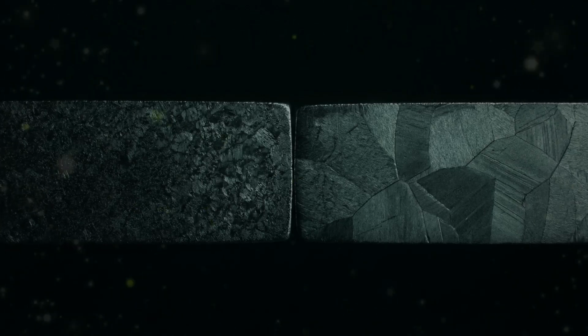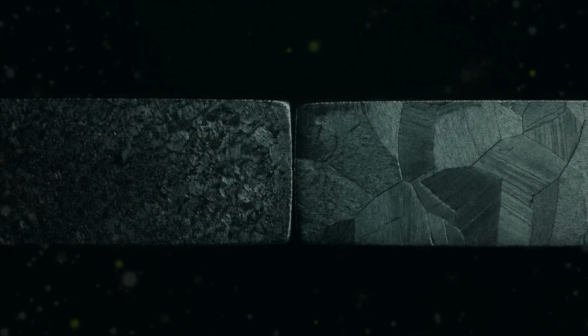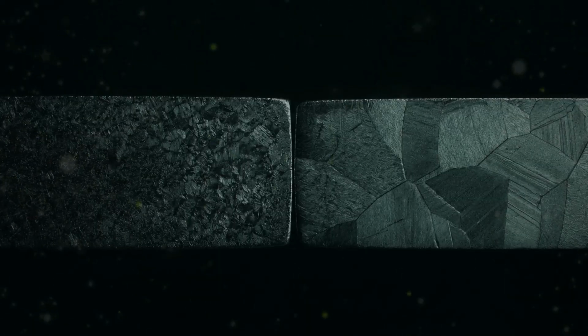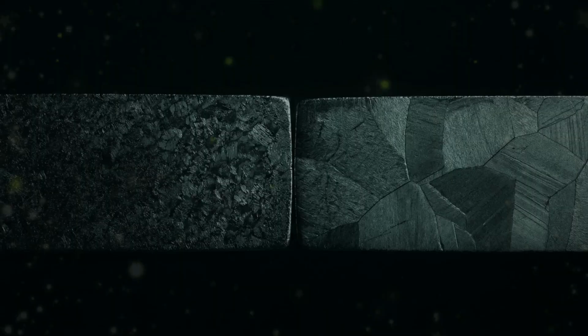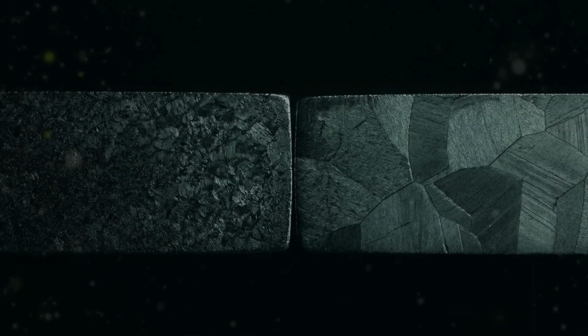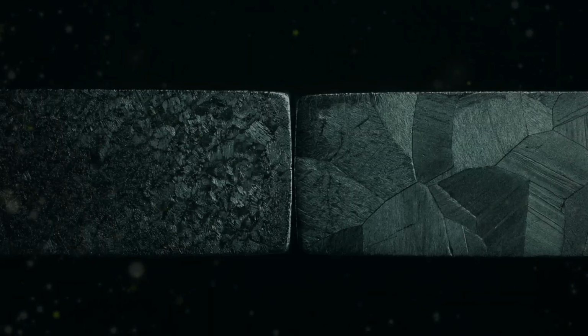Osmium, the densest naturally occurring element, has a density of approximately 22.59 grams per cubic centimeter under standard conditions, marginally higher than its nearest rival, iridium, at approximately 22.56 grams per cubic centimeter. Iridium's extraordinary density is a consequence of both its heavy atomic mass and its compact face-centered cubic crystal structure, which packs heavy atoms together with high efficiency. It is also exceptionally hard and carries a melting point of approximately 2,443 degrees Celsius.